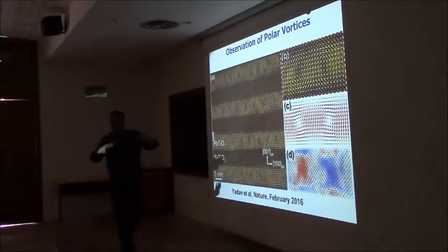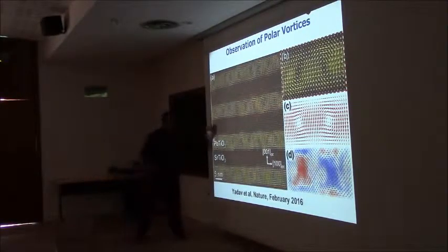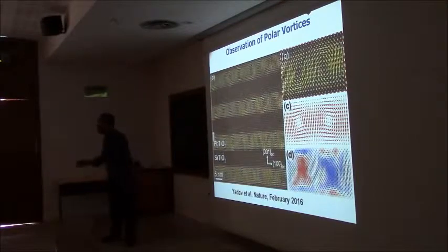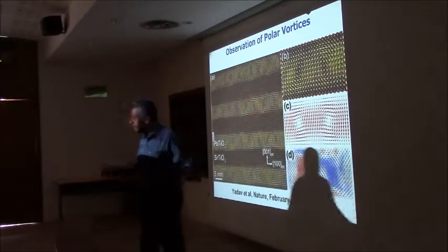This was a 5 by 5 millimeter sample. I took it and I sliced it so that in this dimension it's only 10 to 20 nanometers. It's electron transparent. But in doing that, I've entirely changed the mechanics of the sample. And if you remember that Hamiltonian we wrote down, it had a mechanical component. So my first question was, oh, this may be something to do with sample preparation. And it turns out it's not. I will show you later.